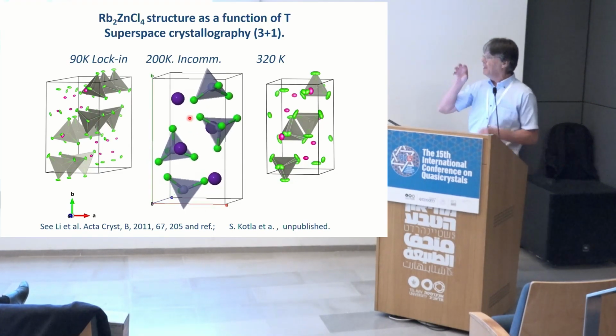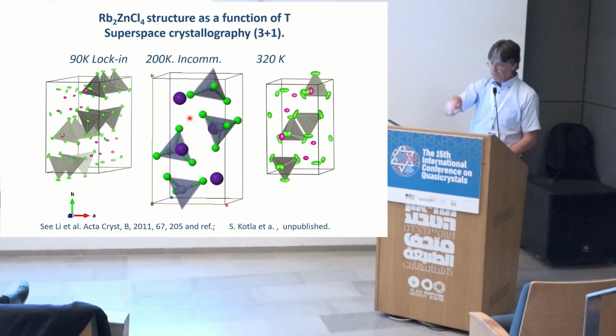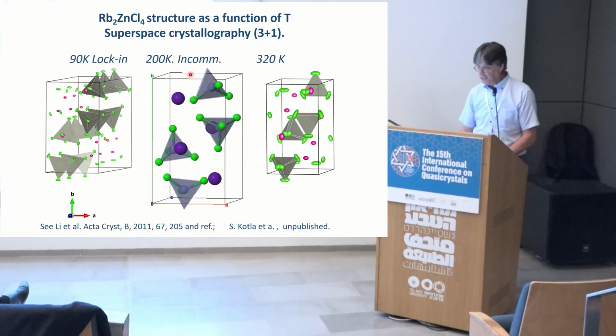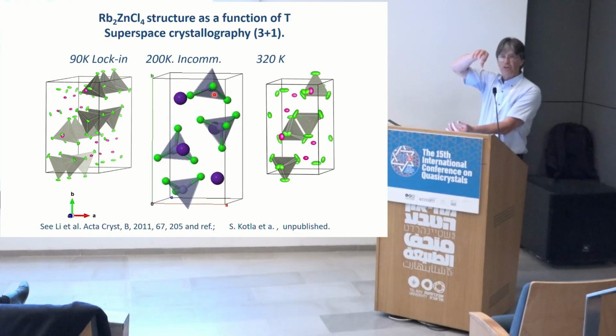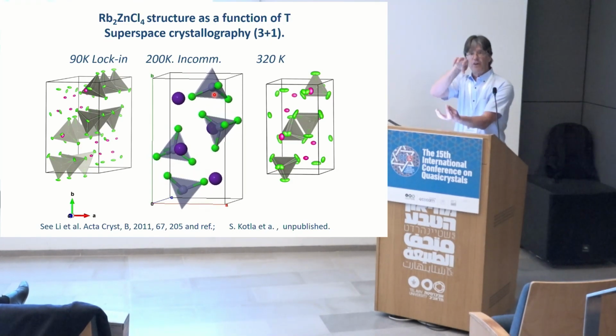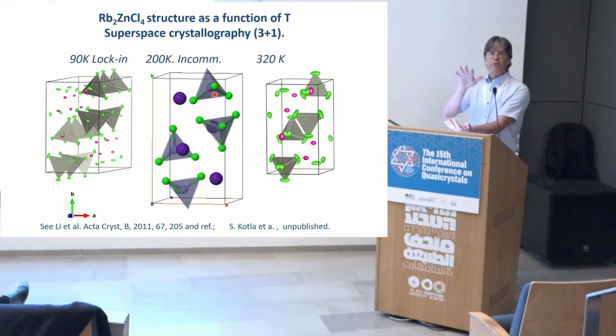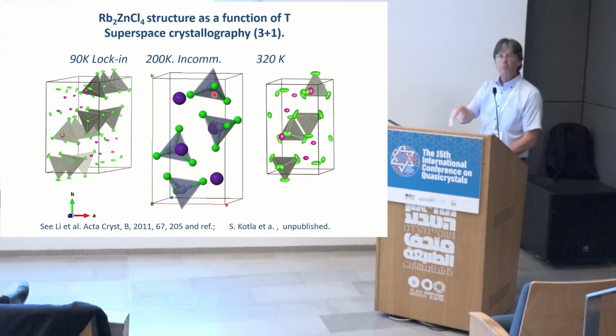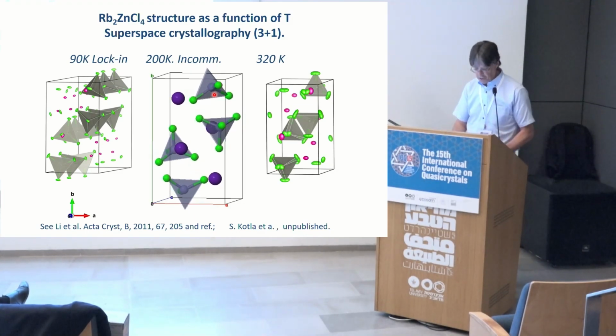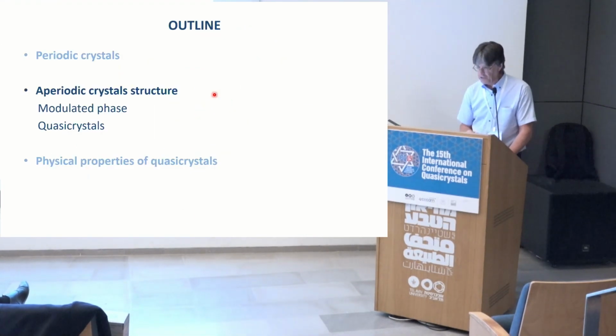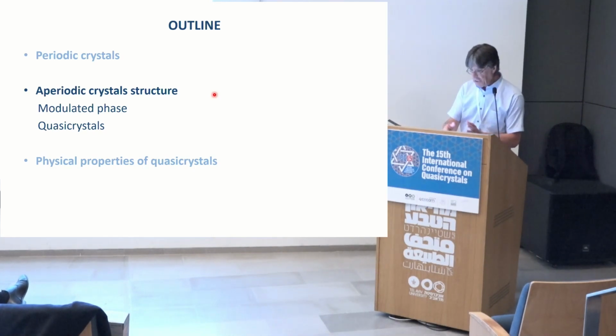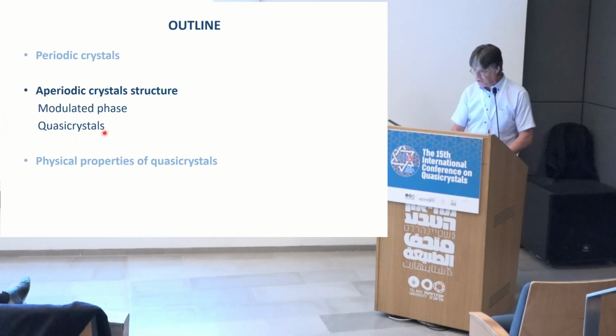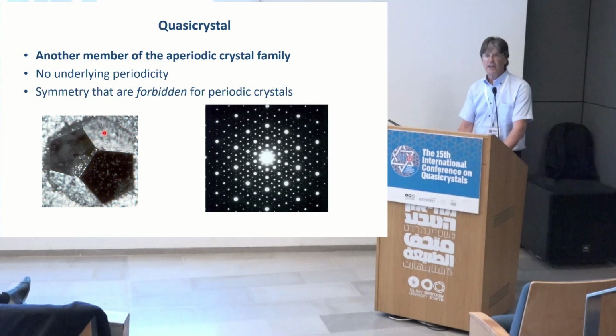And what is shown here is just what is going on if you would travel perpendicular to the screen. You see that the atoms are never at the same position. They jiggle a little bit around two positions and never repeat themselves along the c-axis, which is perpendicular to the screen. So one has a whole set of tools to derive this structure for incommensurately modulated phases. So I will now turn to a more complicated case, which is quasicrystals, which were discovered in 82.